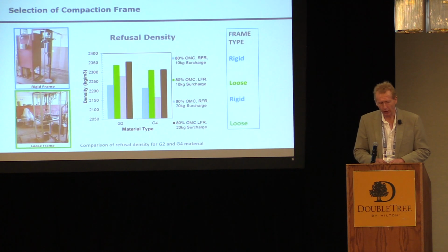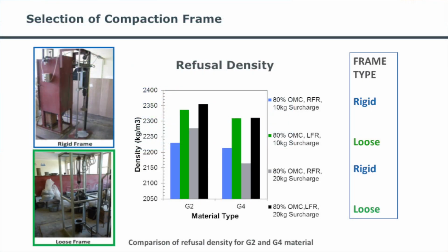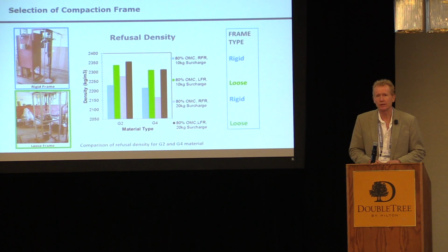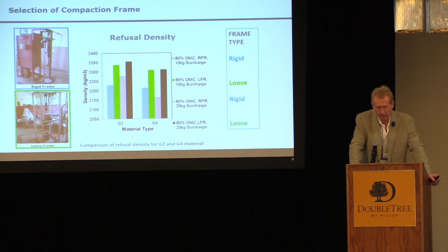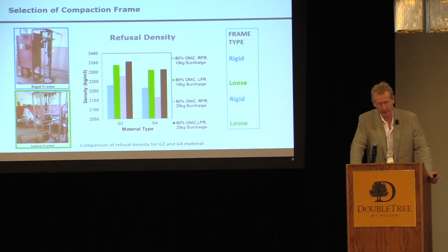We went through a lot of, let's say, teething pains in developing this system with different types of frames, with different types of hammers, and you can see the variability that one gets by just changing the frames and using the same hammers. So it's rather important to standardize this, otherwise one's not going to have uniformity in mix designs between different regions and different projects, etc., etc.